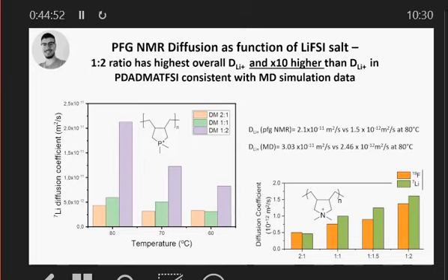Similarly for the DADMA, same order of magnitude. That's very pleasing because simulations are notoriously not necessarily accurate, but here we have good correlation. We see that the phosphonium system should have a factor of 10 higher diffusivity, or does, sorry, which should correspond to a higher conductivity and hopefully better performance in a device. That's still to come. That we don't have yet.